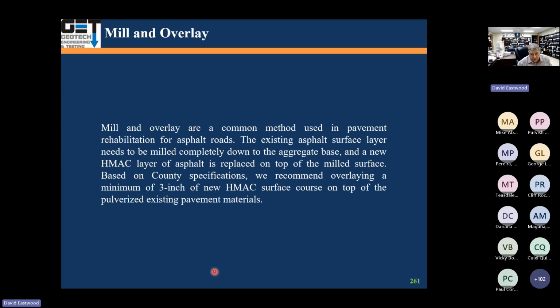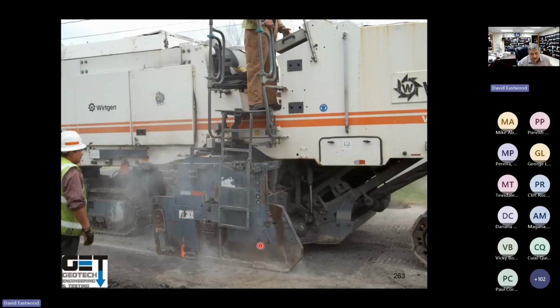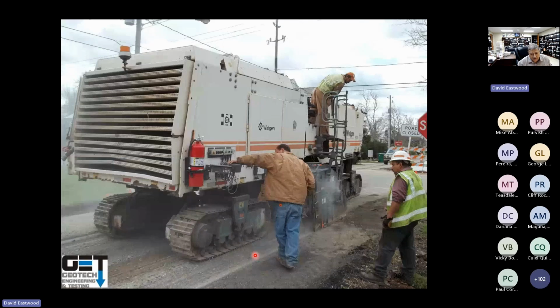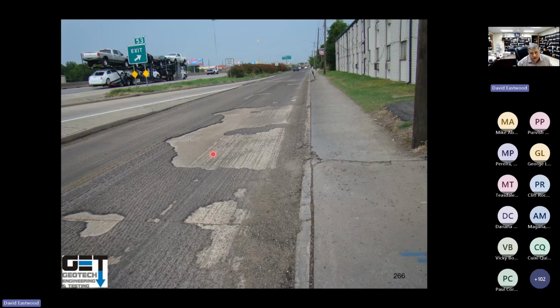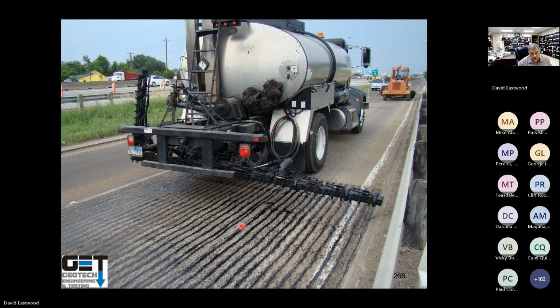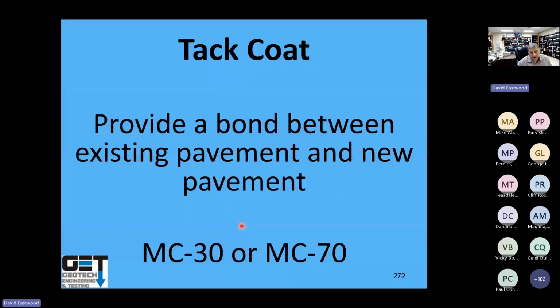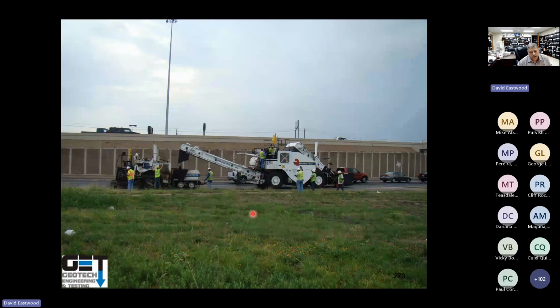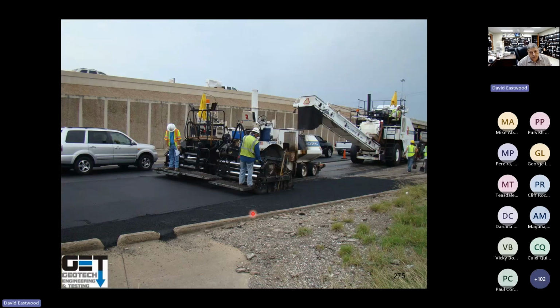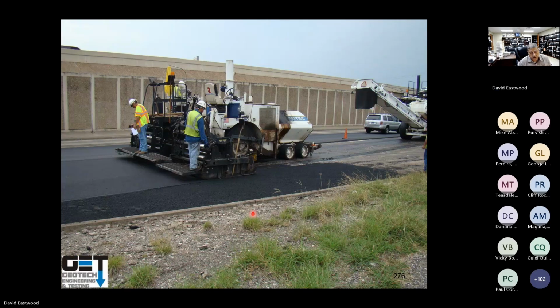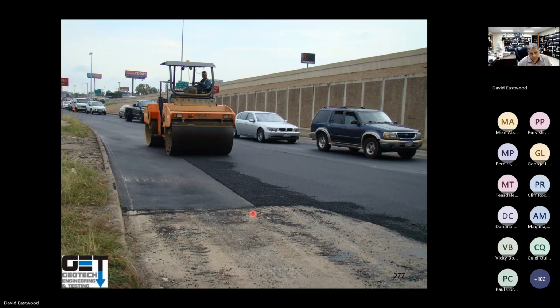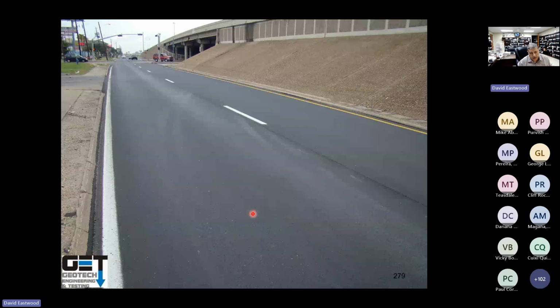In terms of another repair, of course, with mill and overlay, if you have good condition pavements, you go out there and mill the existing asphalt paving with a milling machine. You take out all the asphalt. This is after milling. You go out there and put a tack coat on it. That basically is a binder that attaches the base to your asphalt paving. It's a bonding agent. It's an asphalt emulsion, MC30 or MC70. Bring in your asphalt. Start laying it on there. And then compact it with a steel drum roller. That's what it looks like.